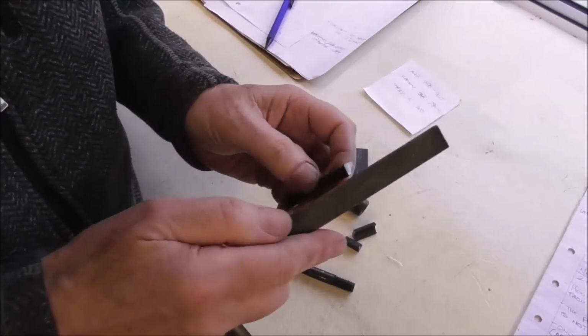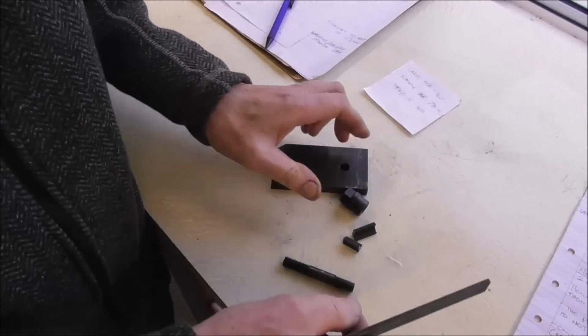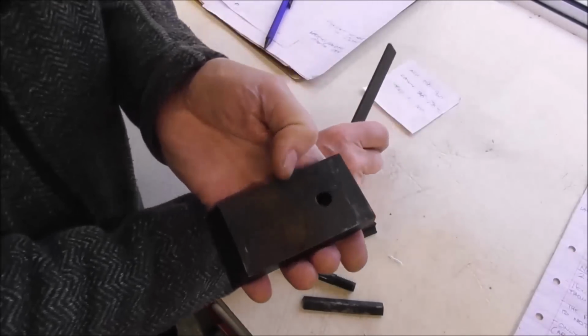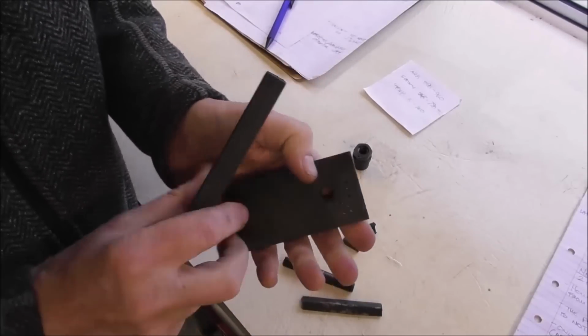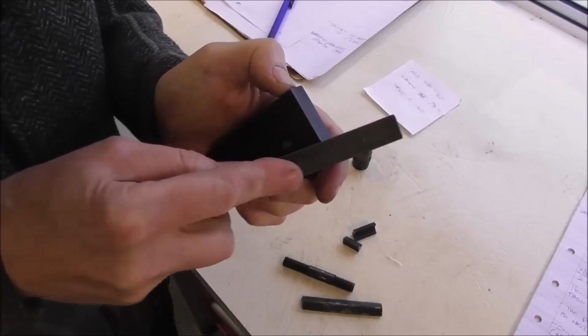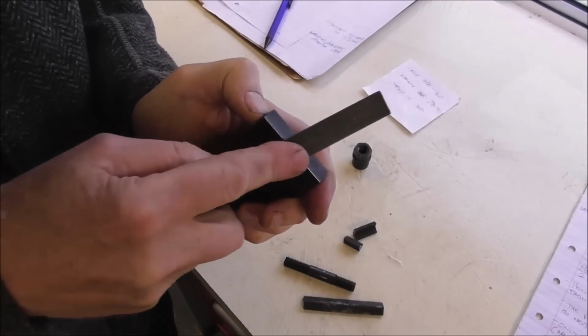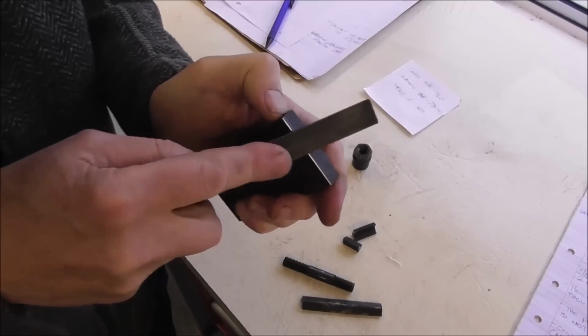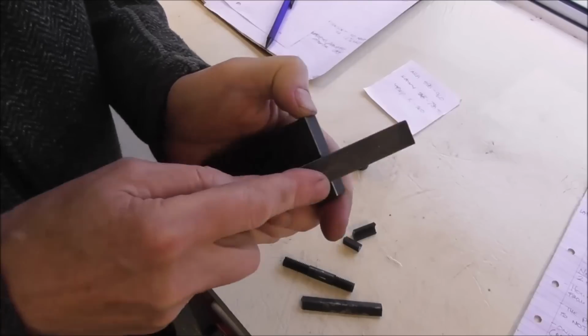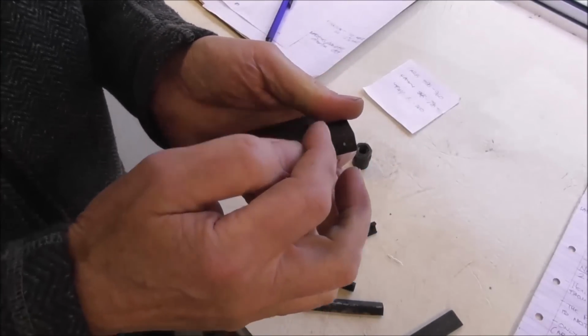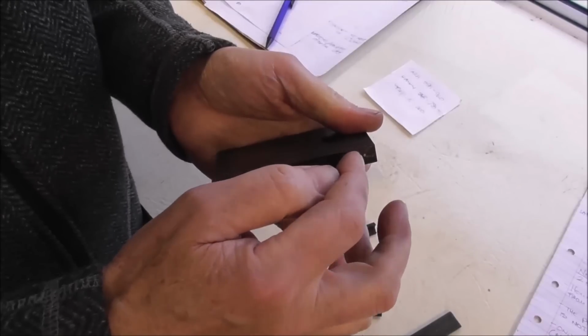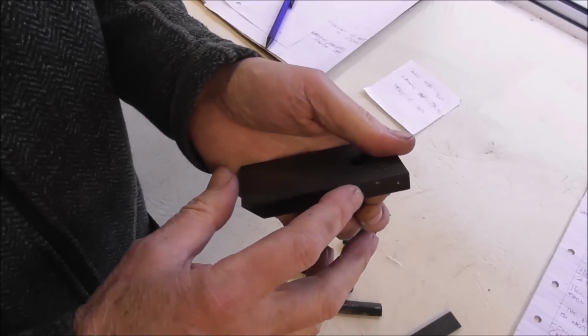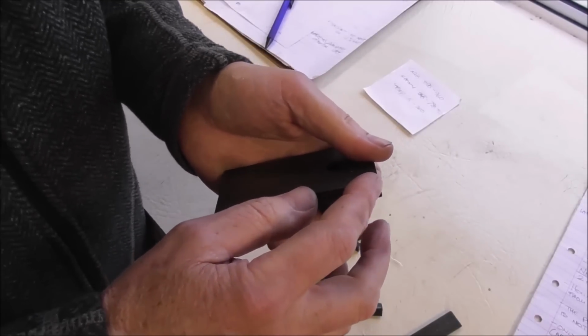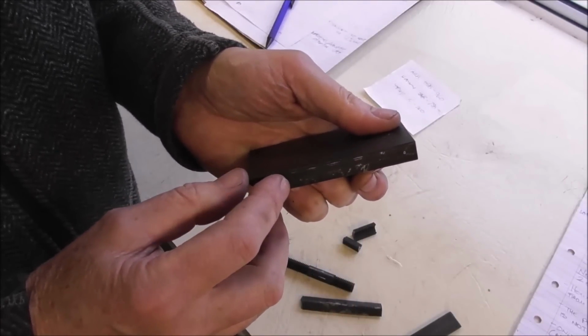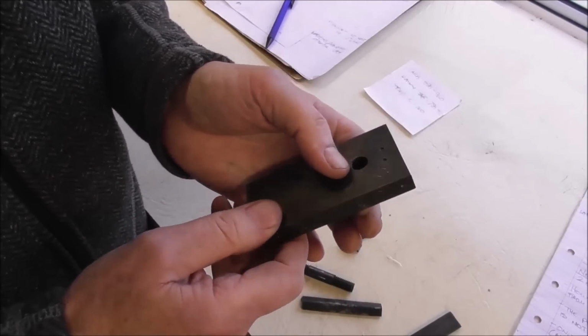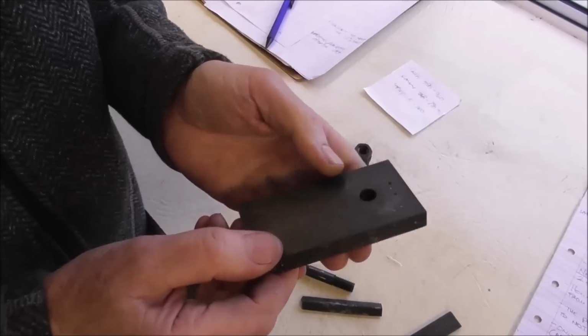These are the parts that I didn't temper, that I broke. That's really glass hard. But the strange thing is, this folder blade or finger part has gone quite a bit softer. I mean, I can file it so it's down below 60 Rockwell C. It feels like somewhere between P20 steel and hard steel, maybe only 40 Rockwell C, something like that. So I was going to grind into it with the surface grinder to see how deep the case is in this part. I could do that on this part down the end that wasn't buried in the charcoal, and down the end that was buried in the charcoal, to see the depth of case. But I can't really do that now because it's been softened too much by the tempering process.